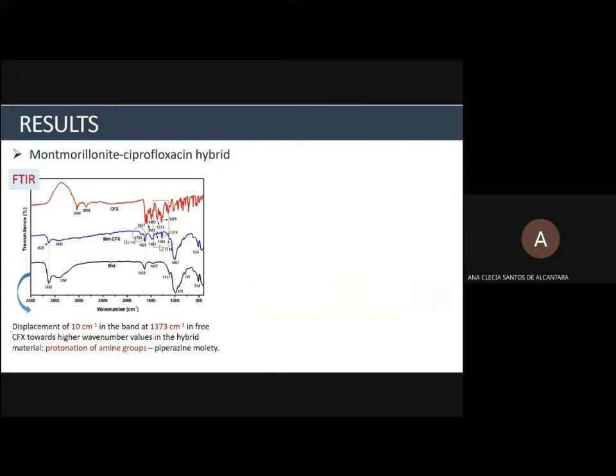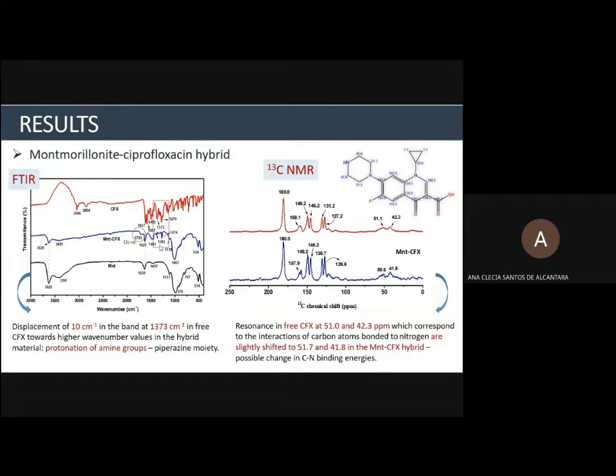The results obtained by infrared spectra can also be confirmed by solid state NMR, 13C NMR spectra of the hybrid material in comparison to free ciprofloxacin in red color here. In this case, the resonances of pure ciprofloxacin at 51 and 42.3 ppm, which correspond to the carbon atoms bonded to nitrogen, are shifted to 51.7 and 41.8 ppm in the hybrid material, which indicates a possible change in carbon-nitrogen binding energies.